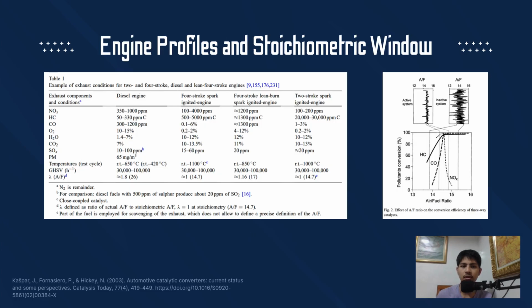As shown in Table 1, different engines present unique chemical challenges. While standard 4-stroke engines are balanced, diesel and lean burn engines operate with a massive excess of oxygen. Our performance data in Figure 2 highlights the stoichiometric window. When the air-to-fuel ratio is precisely balanced at a value of 1, pollutant conversion jumps to peak levels exceeding 95%.